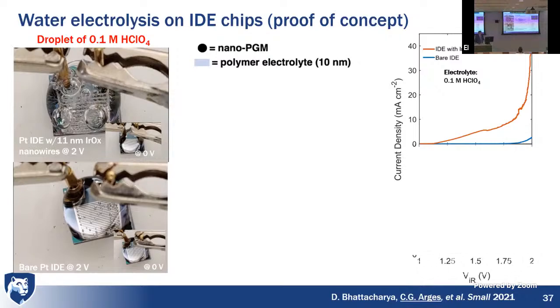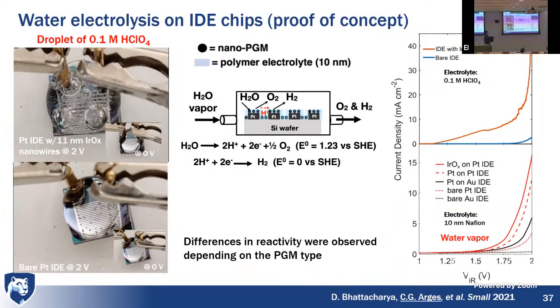But we're interested in thin film polymer electrolytes, so we remove this liquid droplet and we coat it with a very thin layer of that ionomer material, that adhesive that is used in the porous electrode. And we can put different catalysts, and we see differences in reactivity observed depending on the platinum group metal type.